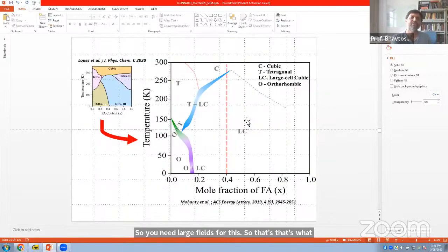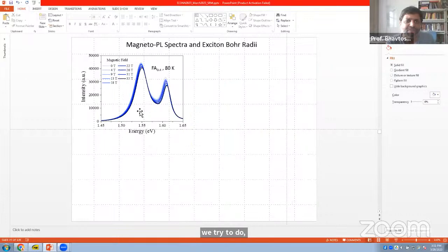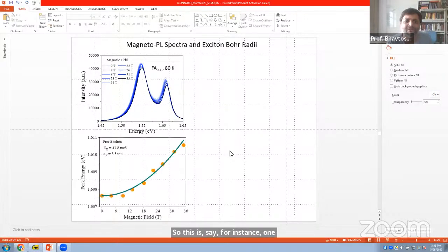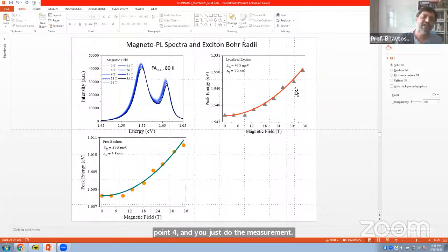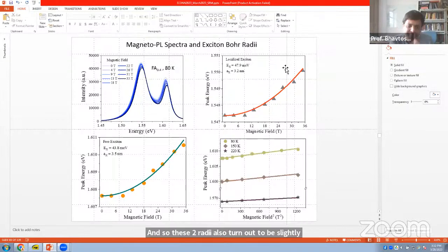So this is what I showed you. Taking one concentration, say FA of 0.4, you do the measurement and you have these two peaks. If you look carefully, this peak shifts a little more with magnetic field than that peak. Since the shift is proportional to the radius, this peak corresponds to states with a larger radius. This is quite characteristic of most semiconductors, where excitons also form shallow bound states. So this is most likely a free excitonic state, and this is most likely a shallow bound state. The two radii turn out to be slightly different, and both seem to have the B-square dependence one would expect from perturbation theory.